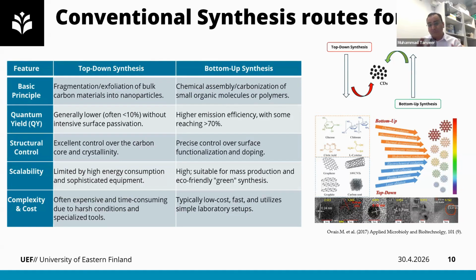So depending on the application, we can select different routes and then we can produce the material and tune up its properties. So there are many options to play with the synthesis routes to establish a particular kind of carbon dots. Also, from the scalability point of view, the top-down approach is not so effective because it requires quite high energy, and it also needs quite sophisticated equipment, so it's very costly. But on the other hand, bottom-up is quite good. It can be used for mass production and an eco-friendly environment.